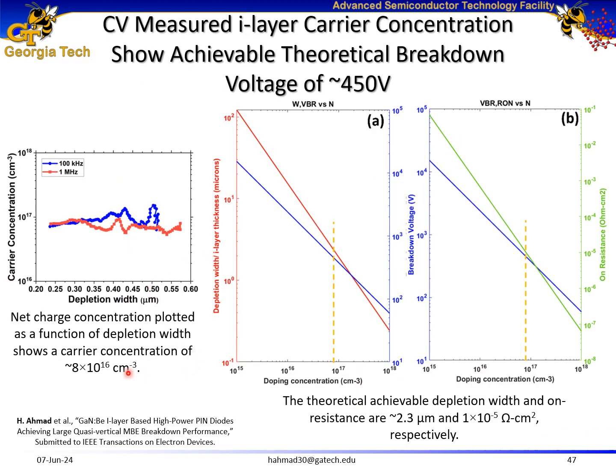From CV measurements, we found a carrier concentration of 8 times 10 to the power of 16 per centimeter cube. And from plotting the equations given in the previous slides, with this carrier concentration represented by the dashed line, the achievable depletion layer width is approximately 2.3 microns, and the achievable theoretical breakdown performance is 450 volts with an achievable on resistance of approximately 10 to the power of minus 5 ohm centimeter square.